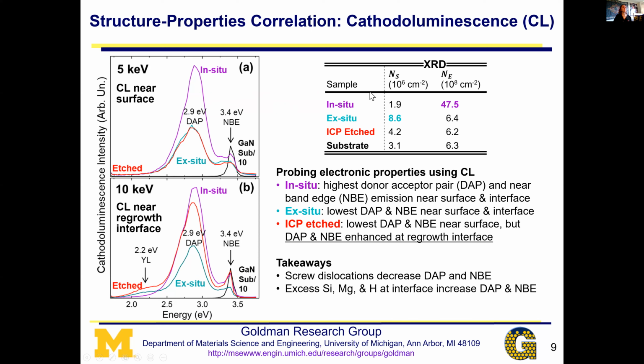And so the correlation between these two trends leads us to believe that the screw dislocations decrease the donor acceptor pair and near band edge emissions. So essentially the screw dislocations decrease or worsen the electronic properties near the interface. And also some work that was done that was outside the scope of this talk is we detected excess silicon, magnesium, and hydrogen at that same PN junction, at that same interface. And we believe that those actually increase donor acceptor pair and near band edge emissions.